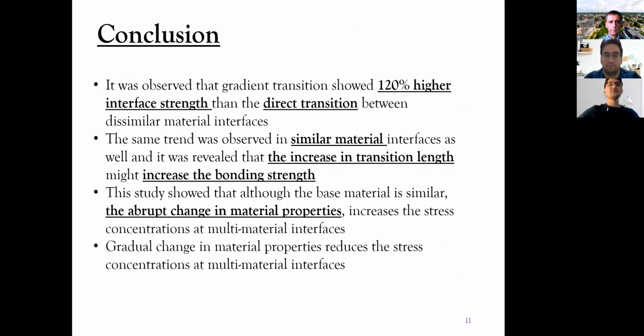Okay, in conclusion, it was observed that the gradient transition showed a relatively higher interface strength than the direct transition between the dissimilar material interfaces. And the same trend was observed in similar material interfaces as well. And it was revealed that the increase in transition length might increase the bonding strength and reduce the stress concentrations. And this study showed that although the base material is similar, the abrupt change in material properties increases the stress concentrations at multi-material interfaces. And gradual change in material properties reduces the stress concentrations at multi-material interfaces. This shows that with the help of the FGAM method, we can enhance the bonding strengths between similar and dissimilar materials. This is my presentation.